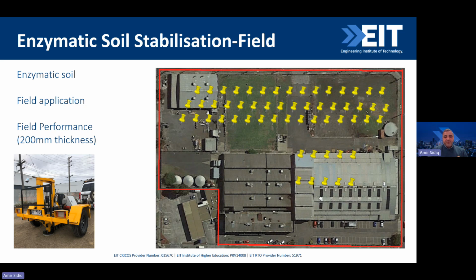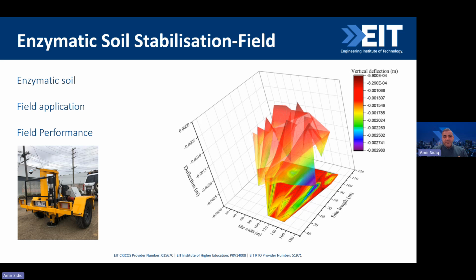Now in that case, this is the ground level, which is 0, and this is the deflection below the site. So you can see here in some spots, we have actually about 2000 micron deflection, and on some other sites, about 700, 800, or maybe the max, the minimum deflection we got actually here is about 400 microns. So this across the site.